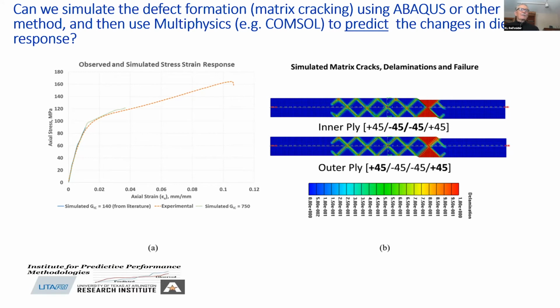Yes, on the right-hand side, we can see for this material regular crack spacing in the off-axis plies, predicted and observed, of course, characteristic damage spacing sometimes called, and the predicted, now these are actual predicted results. The stress strain curve is the little blue curve on the left compared to our red one we've been looking at in uniaxial tension to failure. And these codes are now able to predict the actual values of the dielectric constant that we measure in these specimens as damage develops. And they're actually able to predict the stress strain curve that we should see in the laboratory up to the point where we run out of computational power. So that looks encouraging. We also see this red stuff, and we need to talk more about what that is.